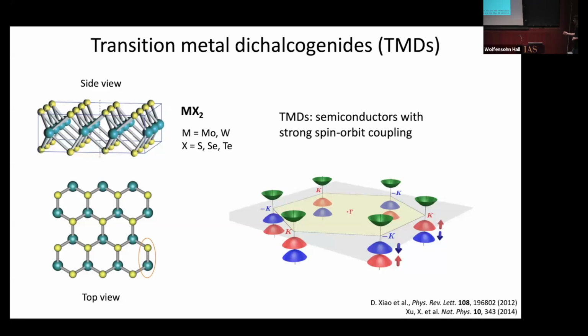Again, the low energy states, at least in the monolayer case, are sitting at the K and K prime points. I guess here K prime is called minus K. These are related by time reversal symmetry, but because many of these are very, very heavy elements, there is also strong spin orbit coupling in these systems. And so what you find is that even though you have both spin and valley degrees of freedom, there's some spin splitting that depends on which valley you sit in: in one of the valleys you have carriers which are spin up, in the other valley, the low energy states have the opposite spin, spin down. And so you have effectively one remaining degree of freedom, so there's a twofold degeneracy in this transition metal dichalcogenide system.